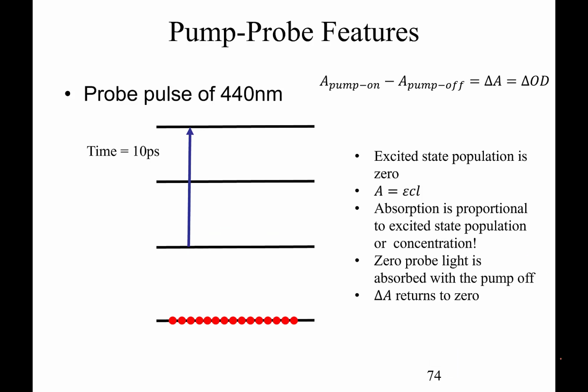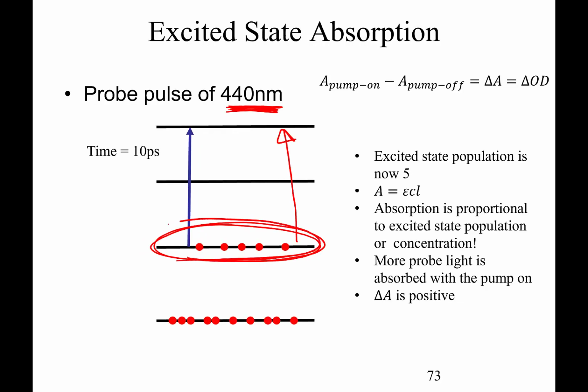Bottom line here is that pump probe transient absorption spectroscopy basically gives us a change in absorbance. If the pump is off, then we don't see any excited states, and therefore the absorbance is zero. But of course, the absorbance is positive with the pump on. So we end up having absorbance with the pump on minus the absorbance with the pump off, and that gives us our change in absorbance. For this particular case at 440 nanometers, we have a delta absorbance that's positive.